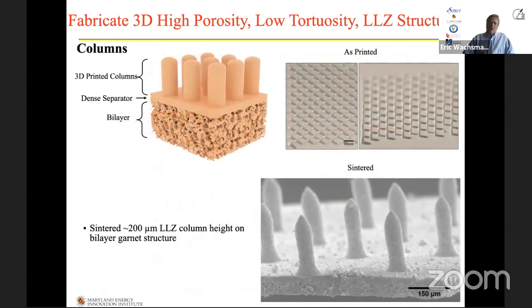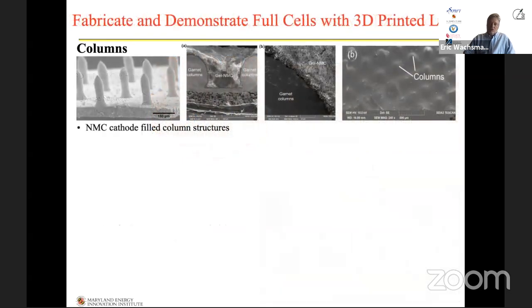This is another structure we made. These are columns. Again, you can see the graphical representation on the left, and then the as-printed photograph, and then moreover, the SEM images of these sintered structures. You can see they're about 200 microns in height, very uniform across that surface. Now what we're going to do is fill them with a cathode material that we'd use in batteries. NMC is a nickel manganese cobalt material. It's very common in batteries. It's one of the higher performing ones.